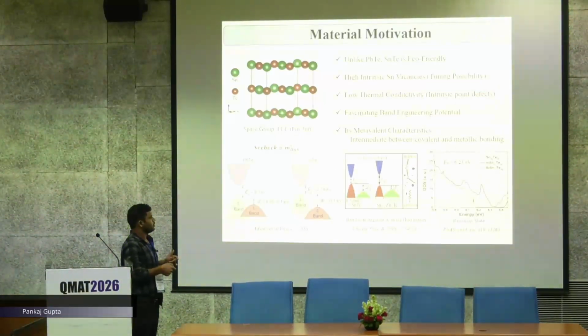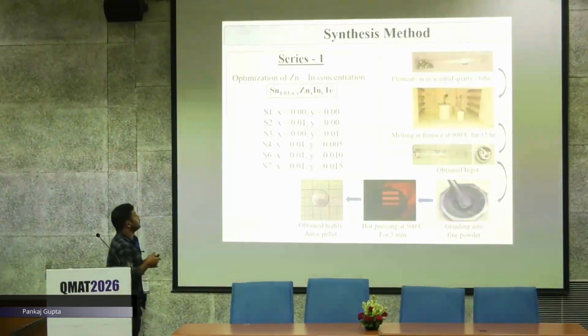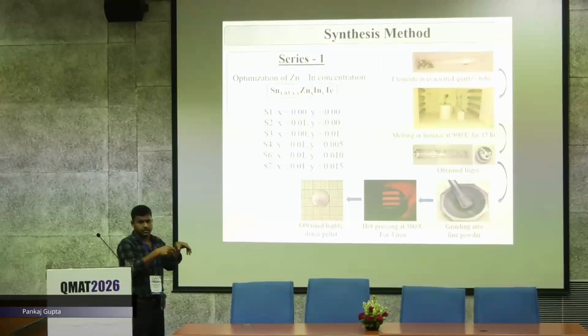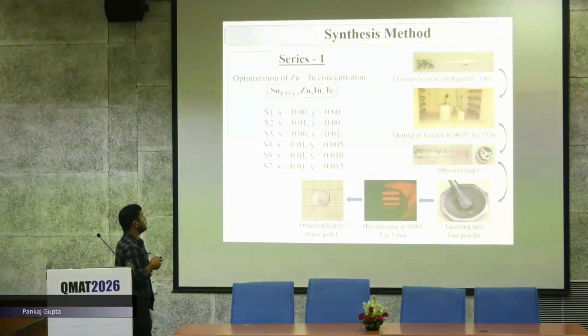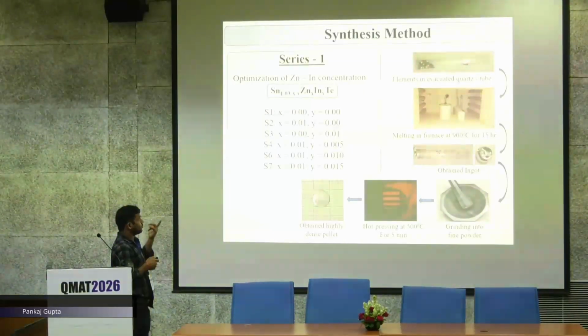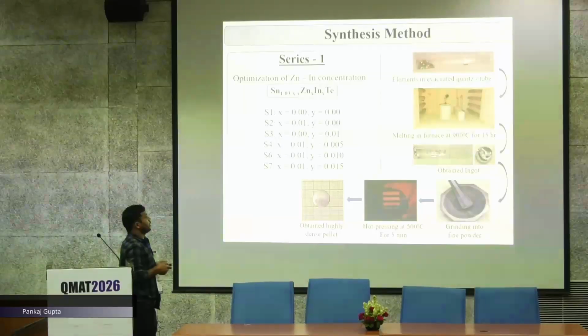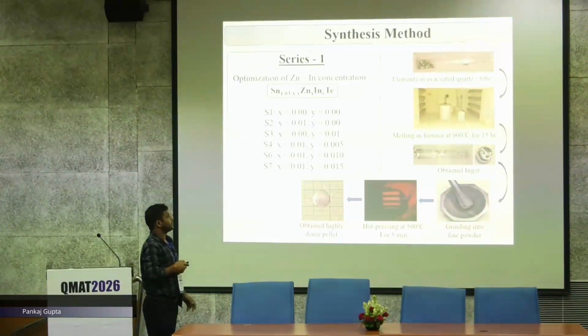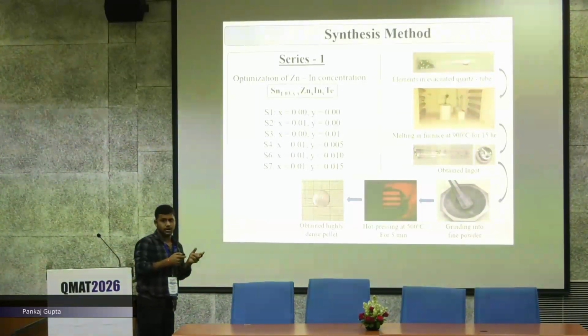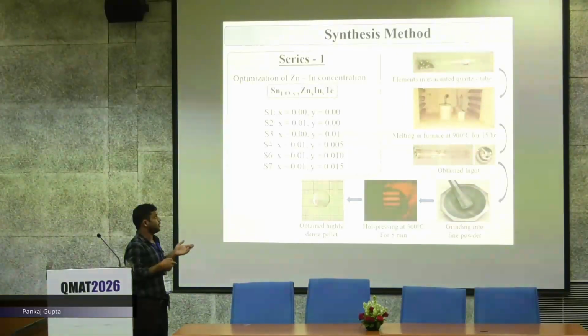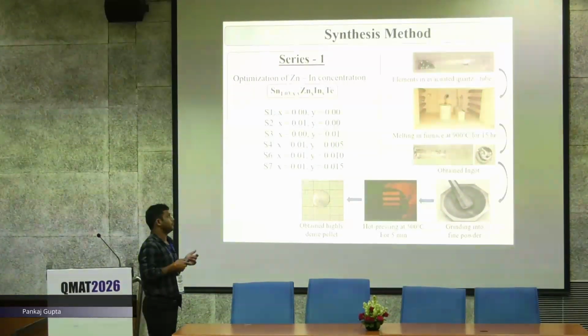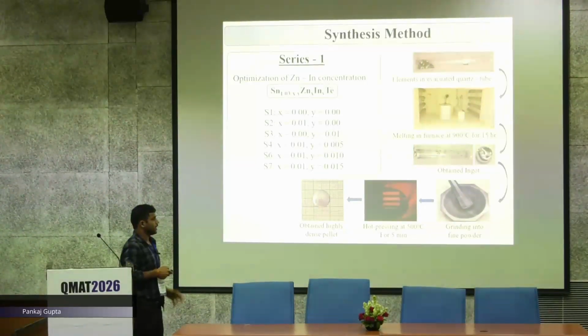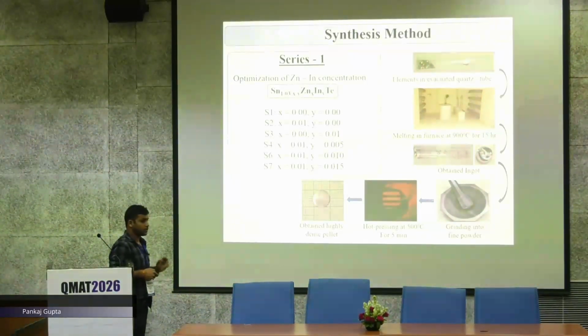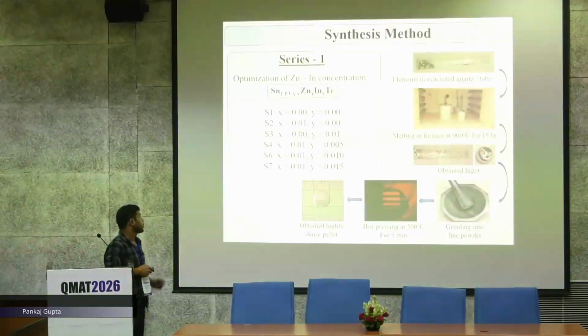Motivated by these two observations, we thought to incorporate both effects in the same material. So for that purpose, we tried to dope zinc and indium together in certain proportion. And how did we do it? For our synthesis, first we took a quartz tube where we took all the precursors in and evacuated the tube, sealing it with a flame. We put it in the furnace, heated it to 900 degrees centigrade, and we got a nice ingot. We crushed it and did hot pressing to get a very high density pellet.